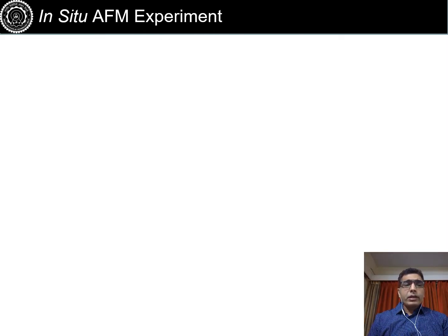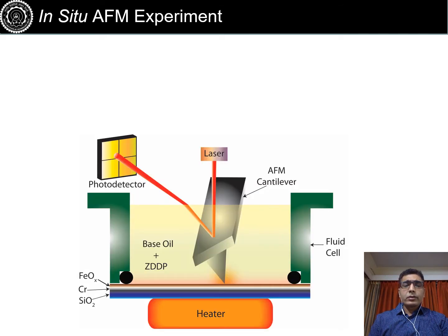But so far there was no evidence of how these films form, exactly what parameters are important for the growth of this film. So we took up this approach based on AFM in liquids, and we conducted an in situ experiment. As I've shown in this picture earlier, we have an AFM based setup which has a fluid cell where we can use a lubricant and use ZDDP in 1 weight percent standard concentration, which has been used in macroscale experiments. And we can use a steel substrate or iron coated silicon surface, which was initially used in our experiments, but later on we moved on to steel as well.